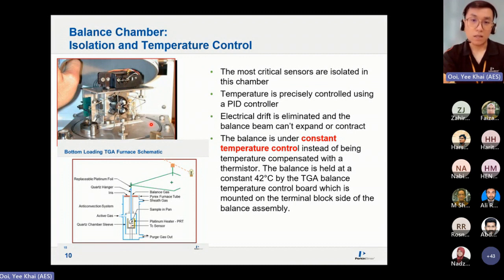So it's isolated and maintained under a constant 42 degrees C. Why is it so? Because you do not want your balance beam to expand or contract according to your environmental temperature, especially if your environmental temperature tends to fluctuate throughout the day. So with this PID control, it's constantly maintained at 42 degrees C, so that regardless of what you're doing, at any given temperature, you will always get the most accurate weight reading of your sample. Remember, in TGA the most important thing is we are measuring what is happening to the weight of your samples.